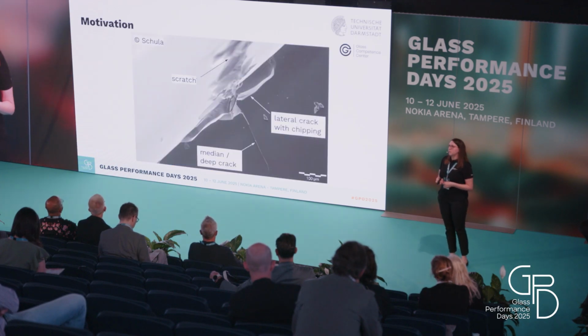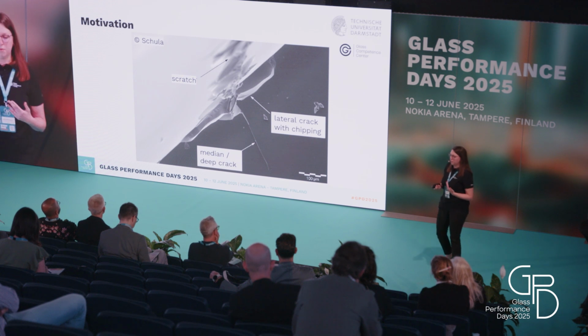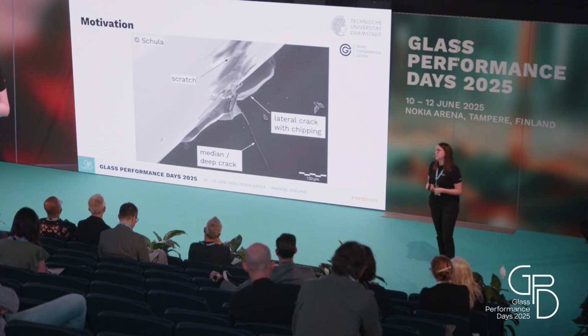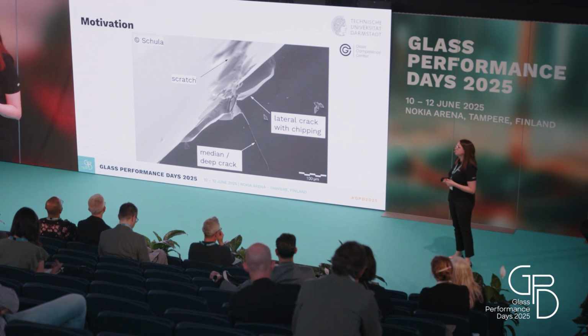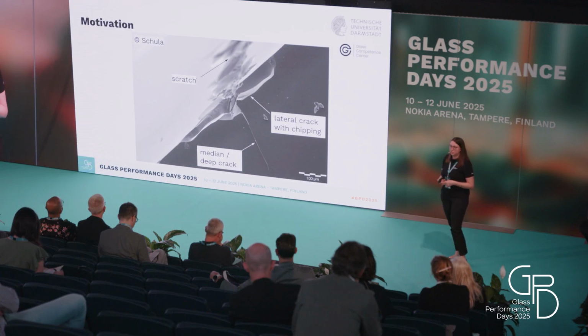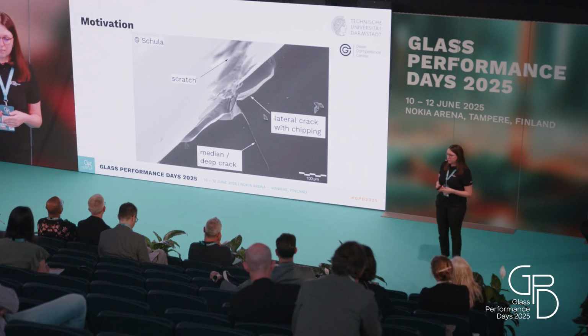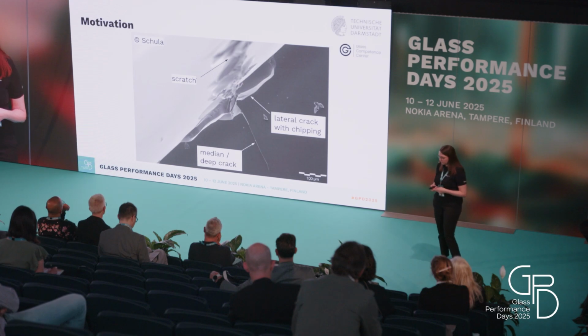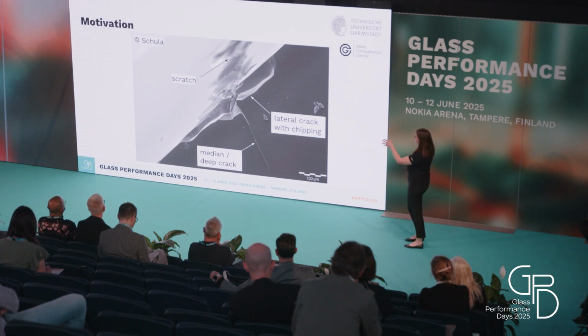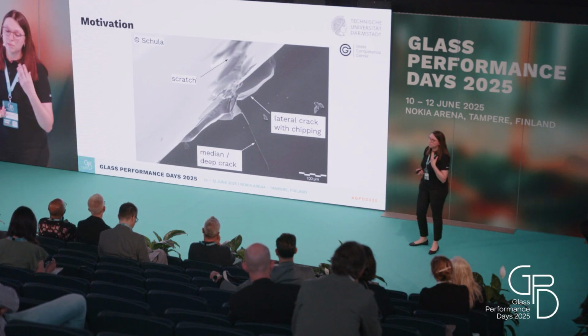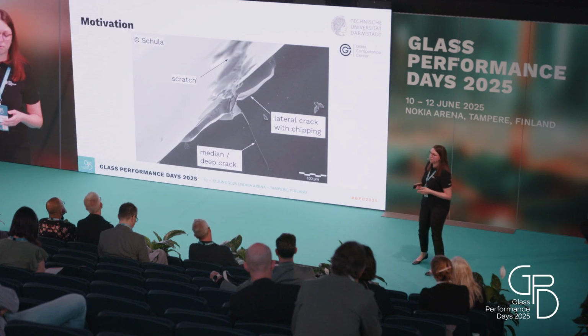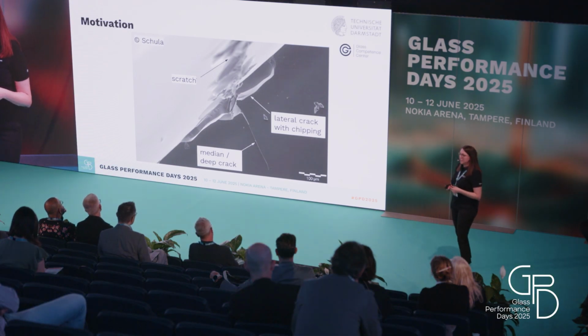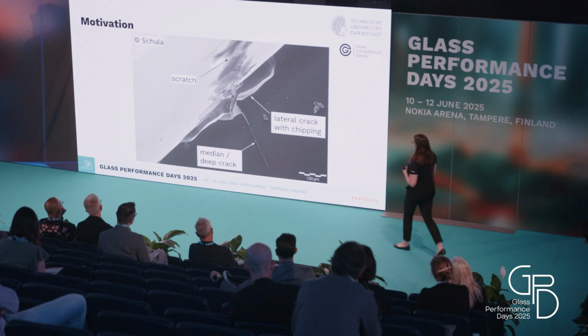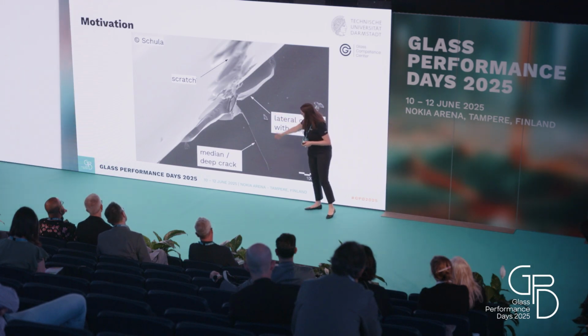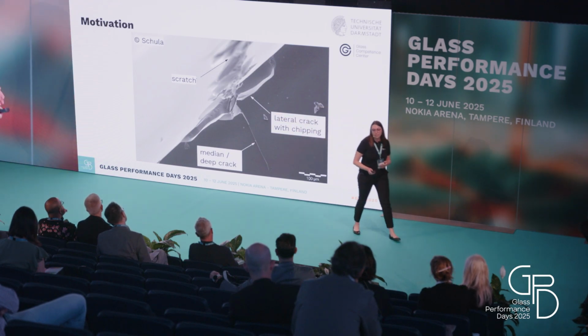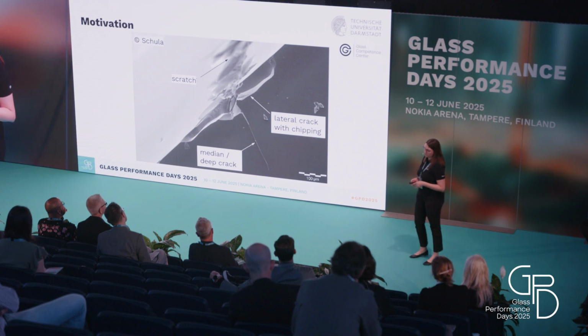When we want to reuse glass or remanufacture something with old glass, then we need to know its performance. And one of the most important mechanical parameters is the strength. In this picture, we see a glass with a scratch. In the light gray, we have the glass surface. And what our naked eye can see is the lateral crack with the chipping. What the naked eye cannot see is this median deep crack, which goes through the thickness of the glass, and exactly that crack is responsible for the strength of our glass.